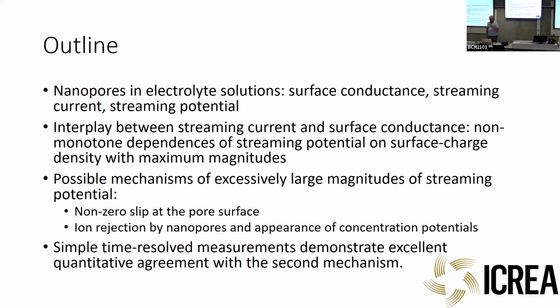But what is important to realize, typically these surfaces are referred to as charged, but basically, no, they are not charged. The system remains neutral. There is a charge separation. What is important is that a part of this charge is somehow bound to the surface, chemically, and another part, compensating charge, is mobile. So this gives rise to interesting phenomena.